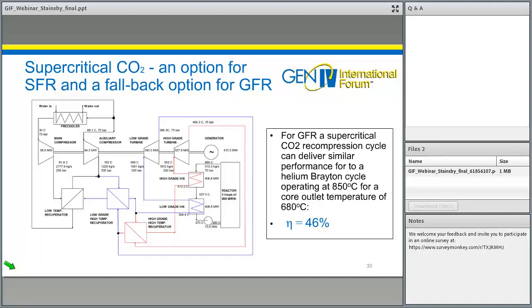And the other advantage of supercritical CO2 is we can actually get quite a good efficiency for not a particularly high temperature. So one of the problems we have with GFR is we may not be able to come up with a fuel technology which is capable of operating in a sustained manner at 850 degrees C, but we might be able to do something which operates at around about 680 to 700 degrees C with more conventional materials. If that was the case, such that we had a moderate temperature GFR rather than a high temperature GFR, then this cycle would return an efficiency comparable to what we'd get with either a helium Brayton cycle or a combined cycle at a temperature which is 150 to 200 degrees colder than the reference design would actually require.